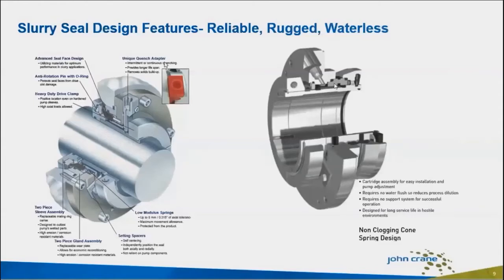And we also use low modulus springs to give up to 8 millimeters or almost 3/8 of an inch axial tolerance. Big numbers. And they're positioned within the seal so that they are protected from the product. Or we also use non-clogging cone spring designs, and the profile of the cone spring assembly has been designed to remain effective and even resist scale buildup or product ingress that would render normal springs or bellows inoperable.